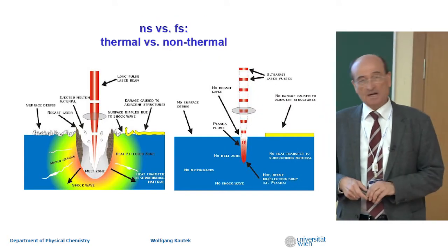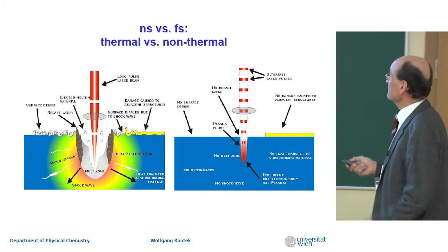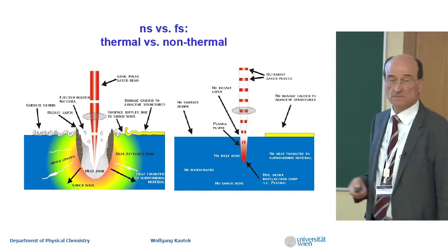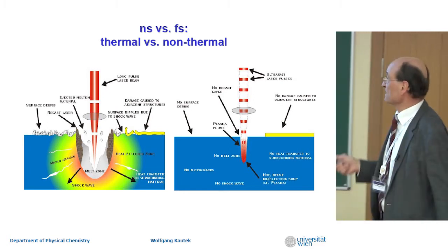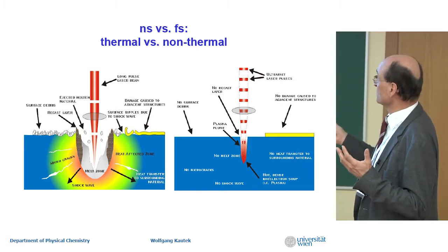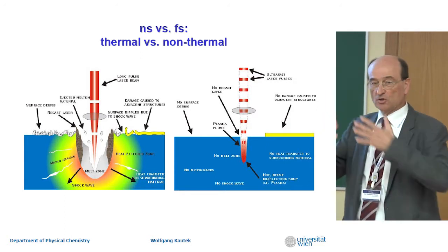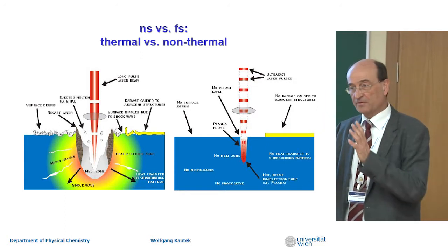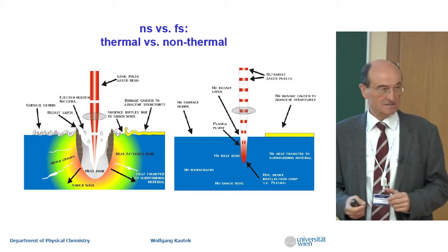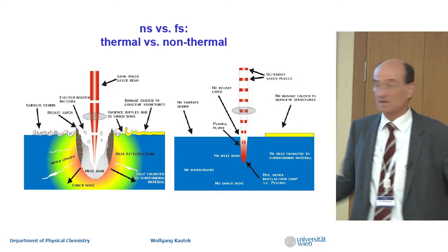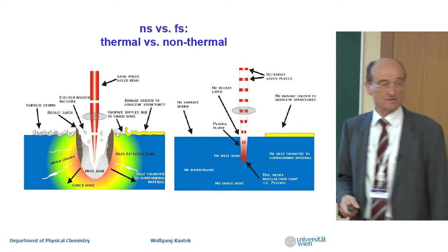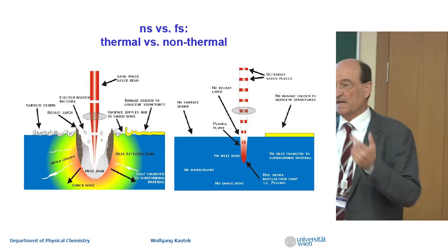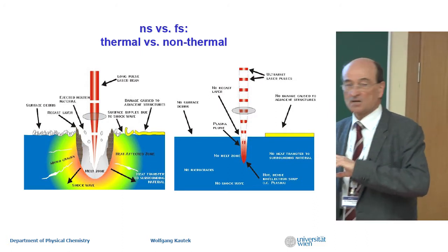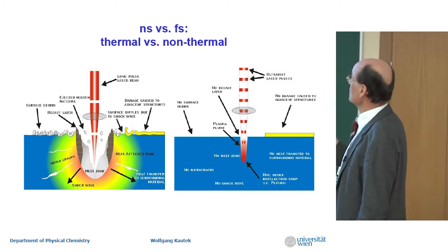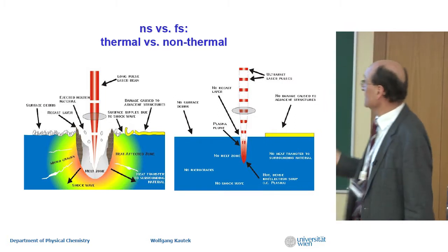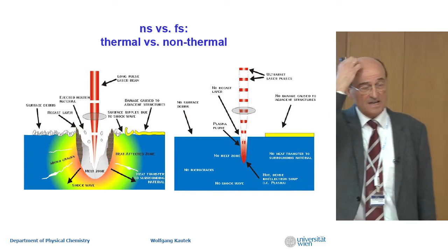Now, interaction. And you will see, I will come back always to the terms thermal and non-thermal. Well, this is just a Mickey Mouse picture to show you if you have long pulses, then you have a long-lasting interaction of the laser light, and therefore heat, which is dissipated there, can travel, diffuse into the solid, as you can see. And you will get the heat-affected zone with all the problems of melting, deforming, splashing, and so on. And if you go to the short pulses, then you're reducing these zones and side reactions.